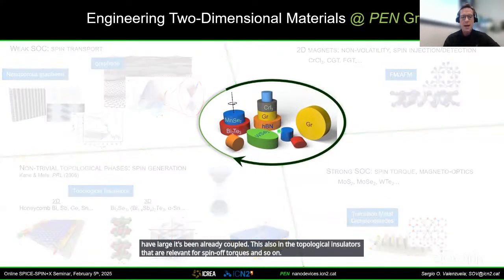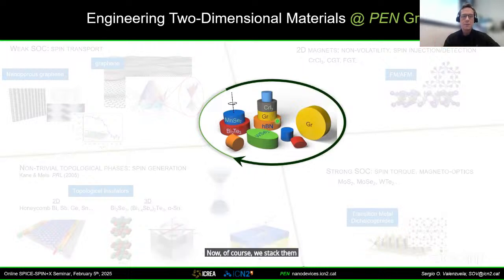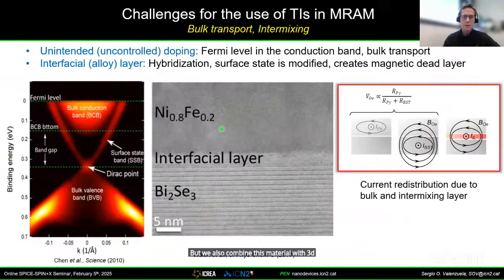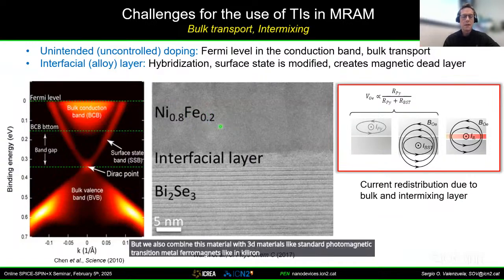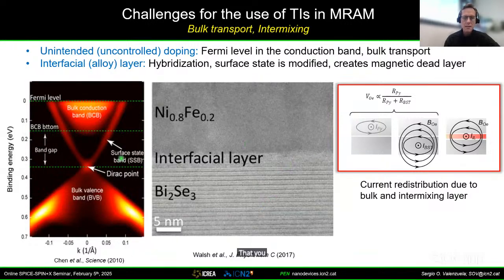Now, of course, we stack them, we combine them, we see the properties together, but we also combine these materials with 3D materials like standard ferromagnetic transition metal ferromagnets like nickel iron or cobalt. And in this situation, you again get the problem that you have in the 3D materials. For example, you can see in this picture from this paper that you have an interfacial layer, an intermix, in between the topological insulator and nickel iron.